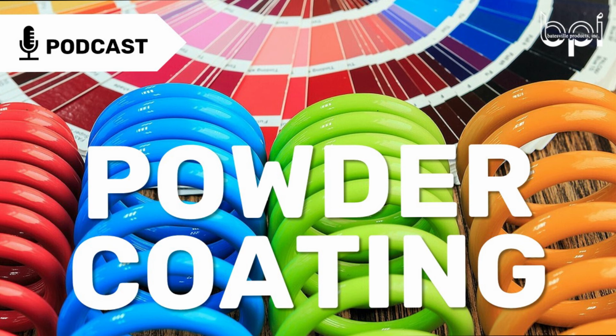Just real quick, let's say there is a reject. Can that part be reworked? Absolutely. You can do many ways of reworking powder. It's going to depend on the powder itself, on the thickness that the powder was applied to, and on where the surface is. If it's a Class A surface, a lot of times it's best to just strip the part. If it's just a given spot on a part, you can sand it, feather it out, and then spray the powder right over it. Powders will intercoat with each other, and sanding and recoating is done every day in just about every shop.